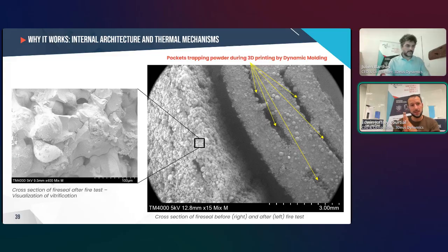At the end of this test, as you can see in this video, our joint successfully maintained its integrity, no flame breakthrough, no residual ignition, and stable performance throughout exposure. These results confirm that our enhanced silicone produced by dynamic molding fully meets the ISO standard for aeronautic and sealing applications. So now to the next slide.